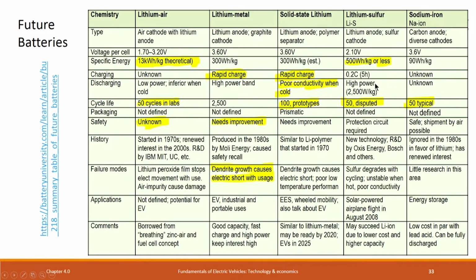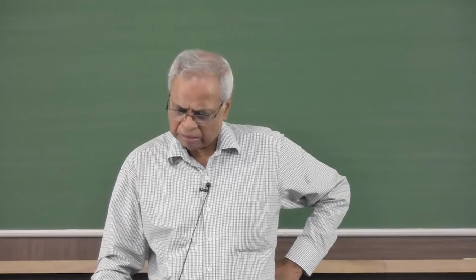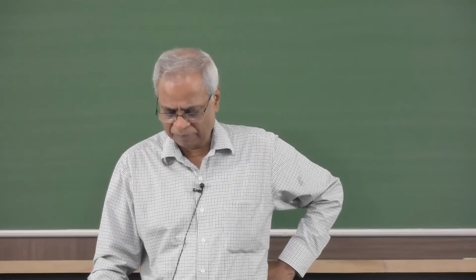Lithium sulfur is another variation. It goes to 500 watt hour per kg, so better. Today, its charging and discharging rate is not good. High power you can do. Cycle life, the only reported cycle life is 50 cycles and that is disputed, whether it was really 50. So, could be even lower. So, yes, good work, something can happen.